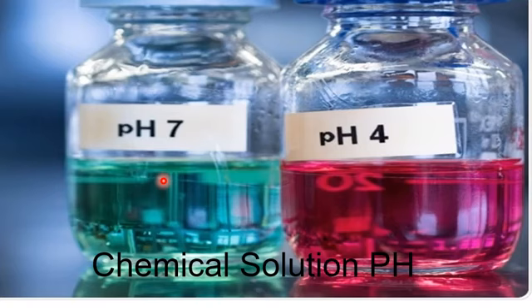But please note that in order to prepare better nanoparticles with a soft gel, soft organic gel, the sol-gel process is done below a pH value of 3. Usually above the pH value 3, the soft gel is converted into a hard gel.